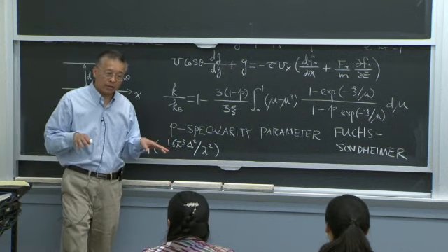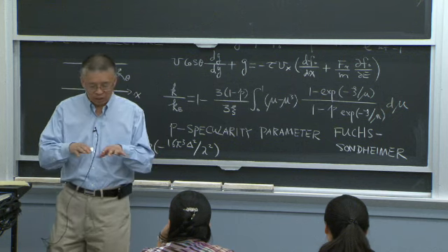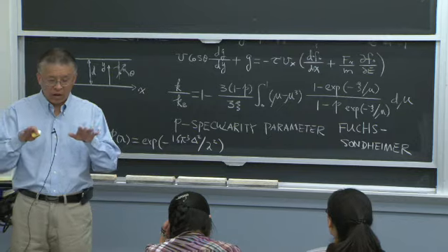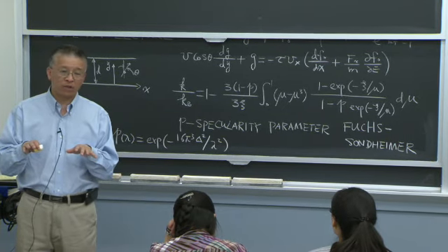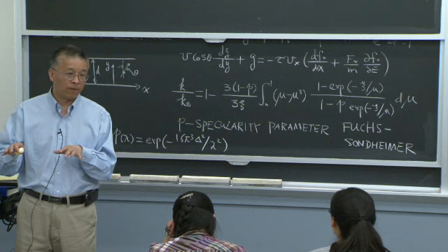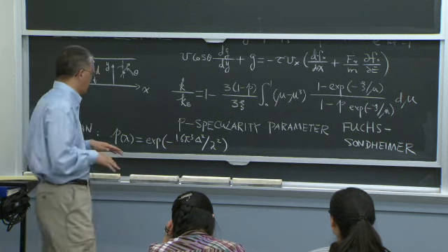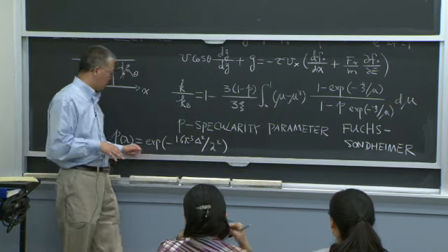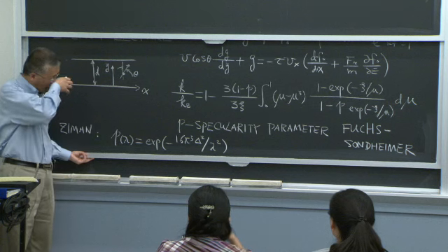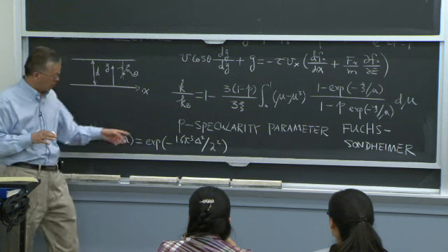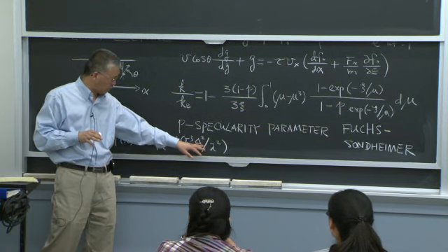Typically in optics, when people say a surface is optically smooth or specular, the roughness is less than 1/10 of the wavelength, right? So if the roughness is less than 1/10 of the wavelength, p is getting close to 1, because the exponent is very small.